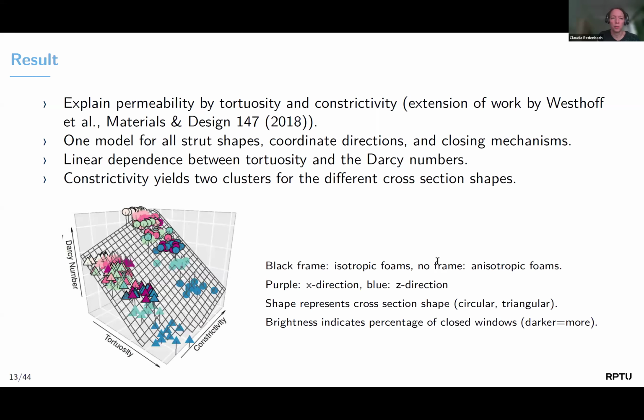Interestingly, we could find one joint model for all cases considered, meaning overall strut shapes, coordinate directions, and closing mechanisms. We had a linear dependence initially between tortuosity and the Darcy numbers, which are a dimensionless version of permeability. And constrictivity could basically explain the difference between the two cross-section shapes, so circles and triangles that we used.